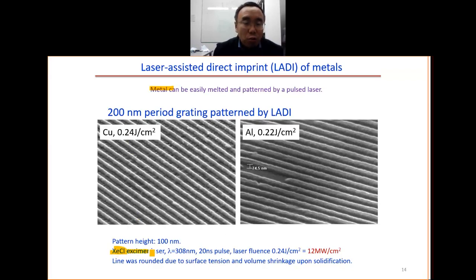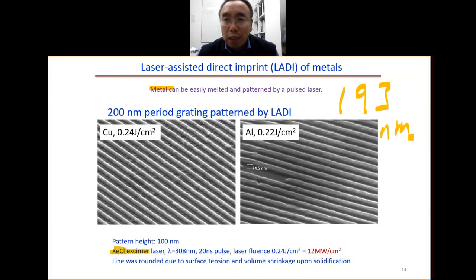By now, you should be very familiar with the excimer laser, because we know that for the lithography, the 193 nanometer one is the argon fluoride excimer laser. This is for the IC manufacturing. For the xenon chloride, you get 308 nanometer. The pulse duration is 20 nanoseconds. This energy here, 0.24 joule per centimeter square, looks like a very low number, but it is only 20 nanoseconds. So you divide this number by this number, you get 12 megawatt power.